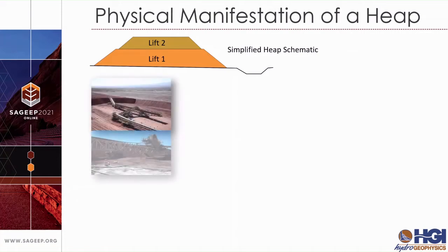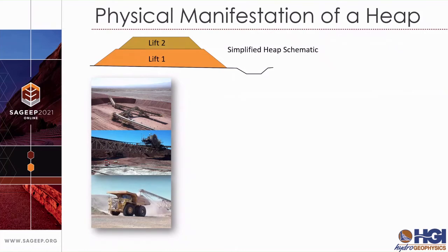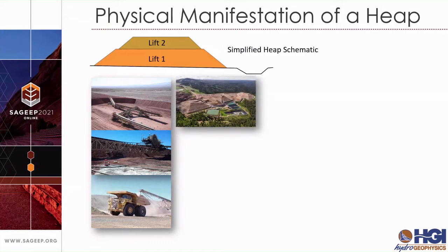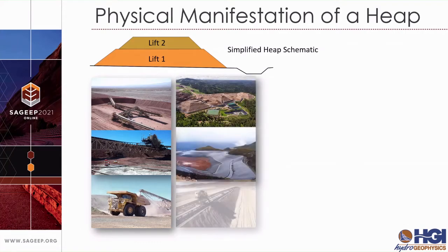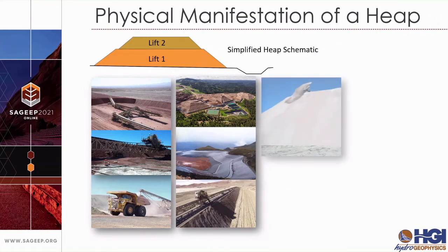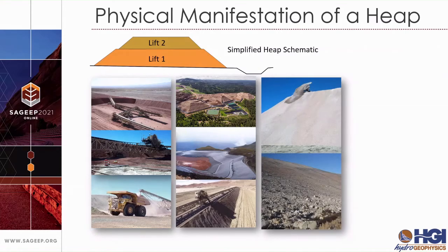In reality, the method of construction, placement, ore makeup, and environment play a role in how the reagent will interact with the ore. Stacking methods in the first column will affect ore density. Heap shape in the second column, whether on a flat surface or filling in a valley, will affect solution drainage and placement ore options. The lift height and grain size demonstrated in the third column may create structural non-uniformities that inhibit or divert solution from contacting all the ore.